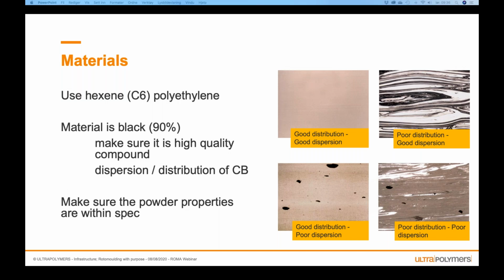I'm now working with a European supplier that is struggling to get the homogeneity of the material 100%. Because if you don't have a homogeneous morphology of the materials, you will have a really bad internal surface. And if you have a bad internal surface, you will have cracks. And all should do ARM impact tests on the materials, on rotomolded samples.